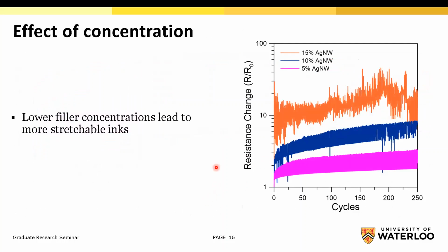Then we studied the effect of concentration. For that, we tried different concentrations of ink: 5% silver nanowire, 10%, and 15%. Here you can see the 5% ink has the minimum resistance change. And that means that lower filler concentrations lead to more stretchable inks. One of the main reasons for that is when you increase the concentration of nanowires, from some point at higher concentrations, it starts to behave like bulk-like properties. So that's why when you increase the filler content, you are reducing the stretchability.